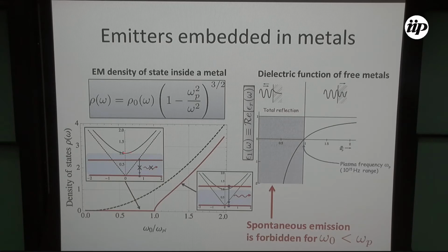So this means that here is my dispersion relation inside the material. If the two-level system has energy smaller than the plasmon frequency, I cannot emit. But if, for example, the energy splitting of the two-level system is larger than the plasmon frequency, then I can emit. So the whole thing is how omega 0 is related to the plasmon frequency.